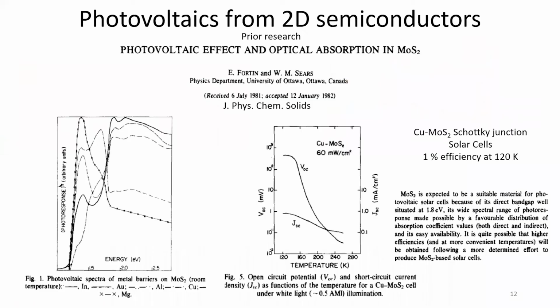And so what I want to do is go back into the past and see when people actually started thinking about MoS2, WS2 and the like as photovoltaic materials. And this was way before I was born. In 1981, there were people at the University of Ottawa, Fortin and Sears, who were trying to use MoS2 for photovoltaics, and they reported the photovoltaic effect and optical absorption in it. They were able to see some very nice photo response. What they had essentially made was some kind of Schottky junction solar cells of various metal contacts made on top of bulk MoS2 crystals.